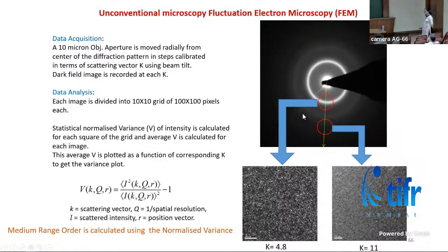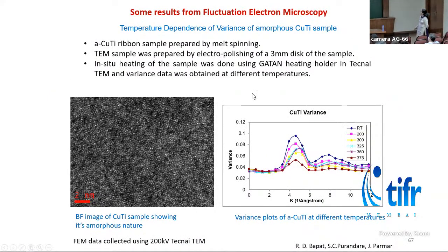So there is hardly any contrast here. That's why we don't see any speckle contrast here. Rudhir has worked extensively on this technique. He wrote scripts to evaluate the variance of the sample. And we have studied copper titanium bulk metallic glass using this technique.